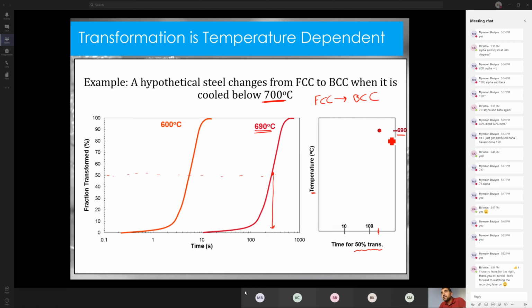What happens at 600 degrees? And just like the example with the water, the more you cool the water below 0 degrees, the faster it freezes. So the same thing here, the more I cool this material below the equilibrium point, so the equilibrium point is 700 degrees, the more I go below 700, the more and more likely this material is to transform to BCC, and the faster this will happen. So we see on the diagram here that the whole thing is now done within 10 seconds. I can put that piece of information on my diagram here. So 50% transformation took about 2, 3, 4, 5, 6 seconds. So I'll put that here, 600 degrees and 6 seconds over here.